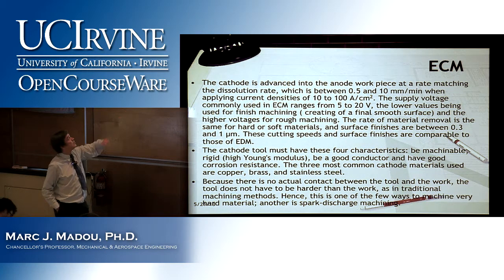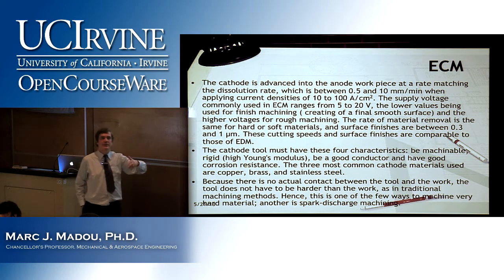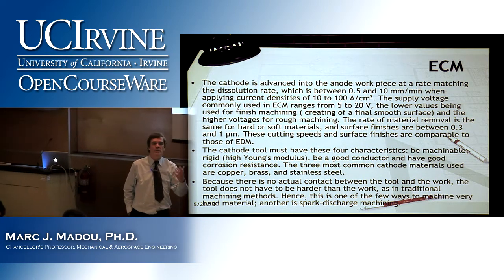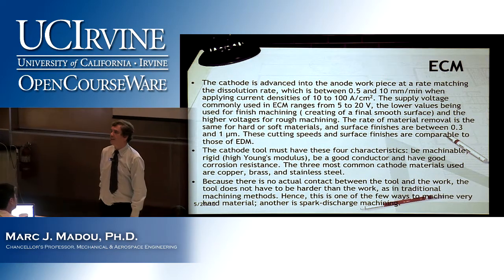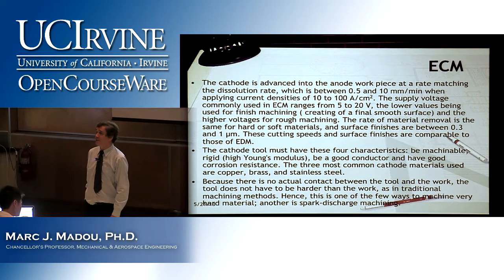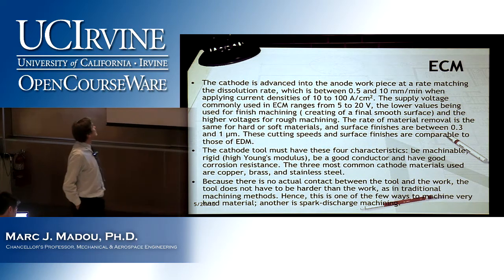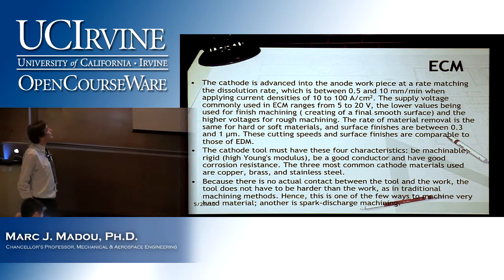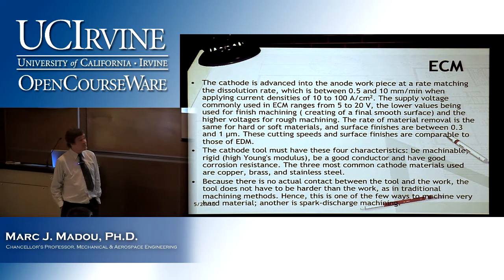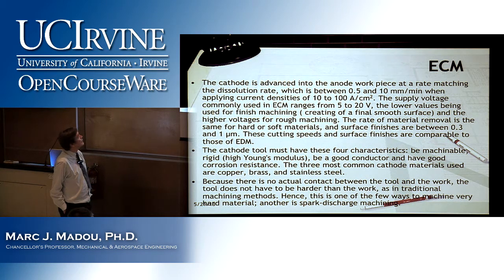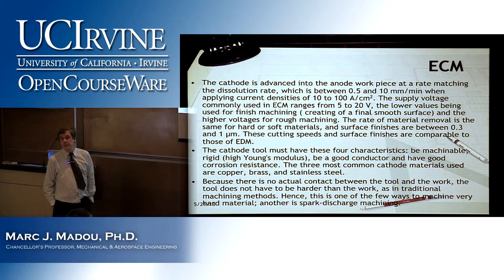High current densities though, eh? That's why you can have that heat produced, because normally in an electrochemical cell, well, you know, you have batteries, right? You have to draw a lot of current before it becomes hot, before it heats up. But once you talk about 10 to 100 amps per centimeter square, you sure have a lot of heat there. So supply voltages are pretty low, right? 5 to 20 volts. And the lower values being used for finish machining.